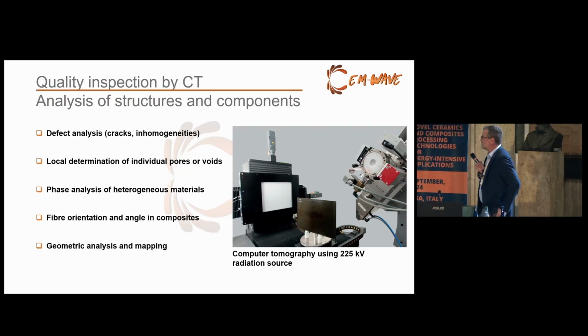Of course, we also did computed tomography on these parts to make before-and-after analyses. Even when you take a tube to industrial high temperature applications, you can take this identical tube and make a post-mortem analysis with computed tomography, and look at impurities or small delaminations or pores, and see whether there is any enlargement of the delamination, or whether the pore region develops cracks and so on. And this is a nice thing.